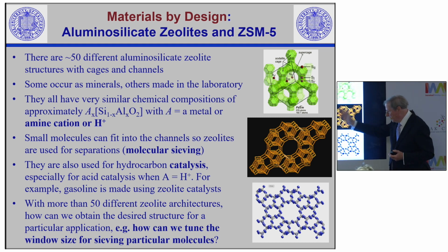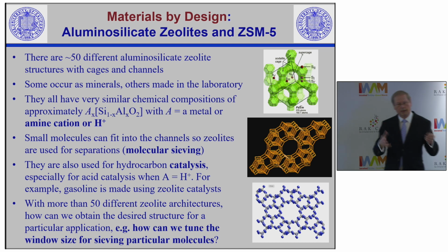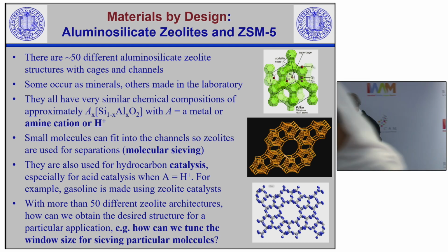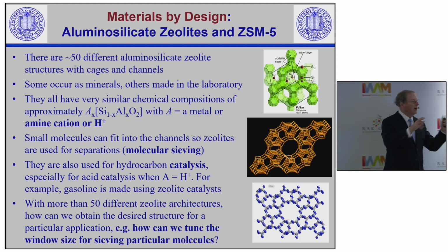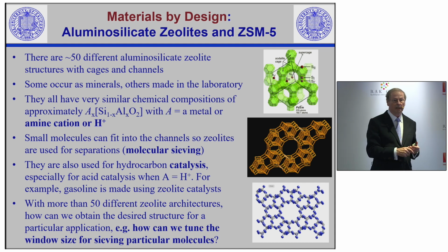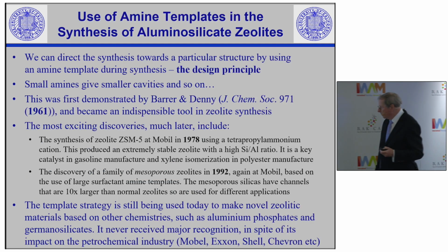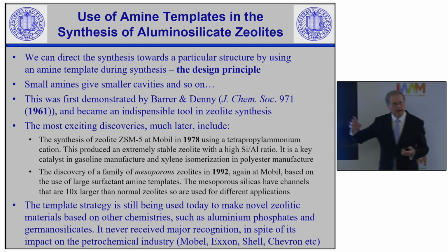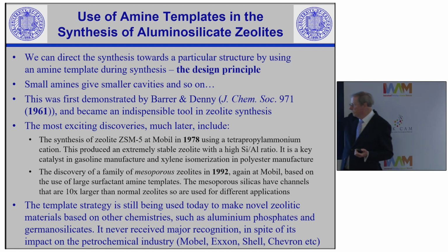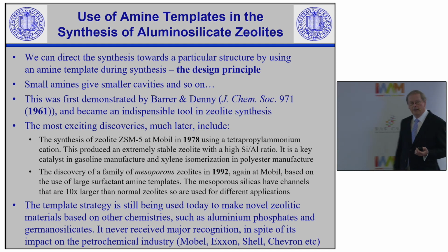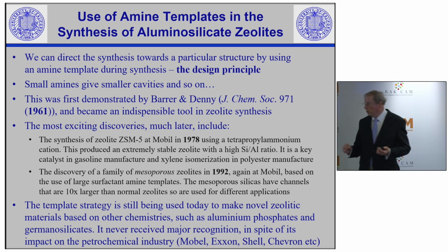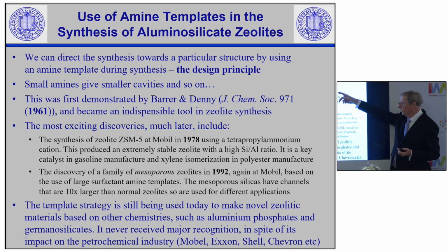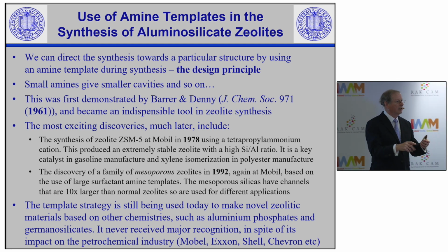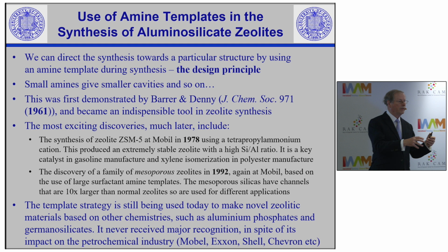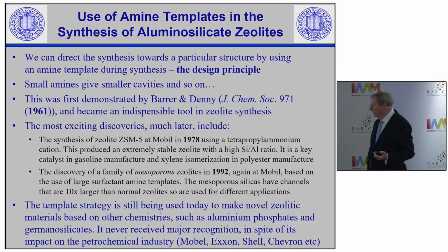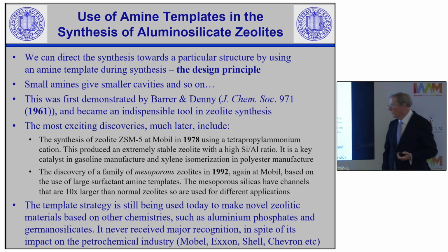And so the question is, if we want to use them as a sieve for a particular application, how do we control the size of the cavities and get the architecture of the molecular sieve that we want for that application? That problem was originally solved by my academic grandfather, Richard Barrer, who was at Imperial College. He did this work about 60 years ago and showed that you could use amine templates, just small amine cations that get trapped in the cavities. If you use a little cation, you get a little cavity. If you use a big cation, you get a big cavity. That was well known, and that's the design principle.